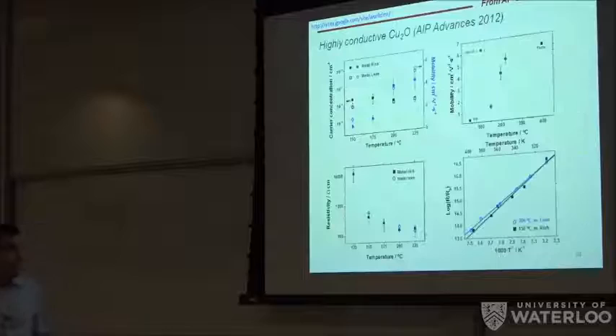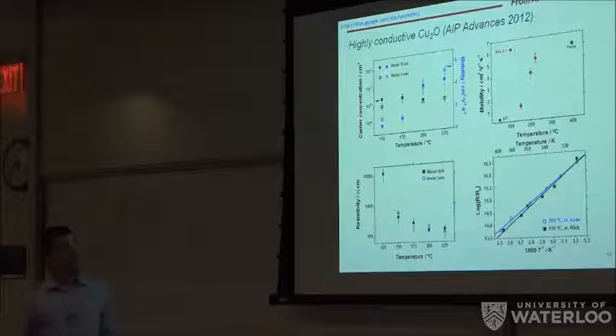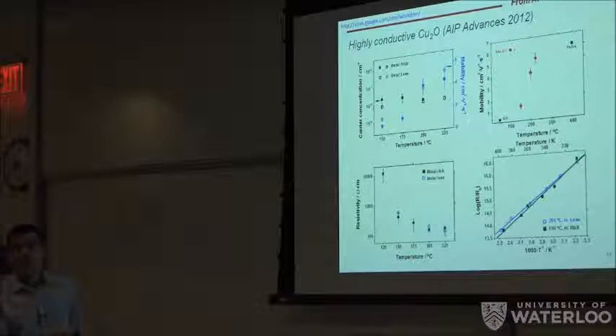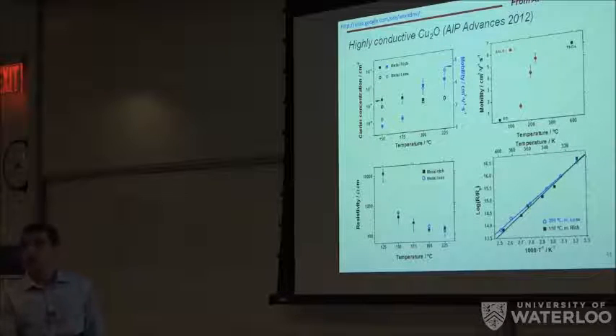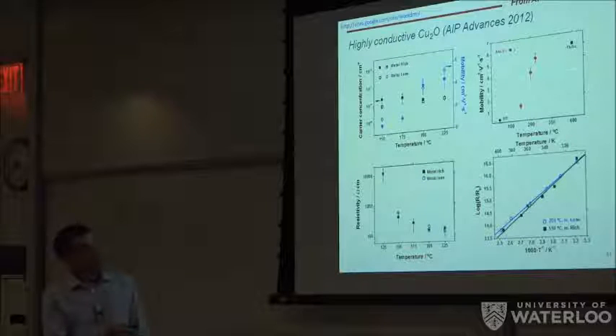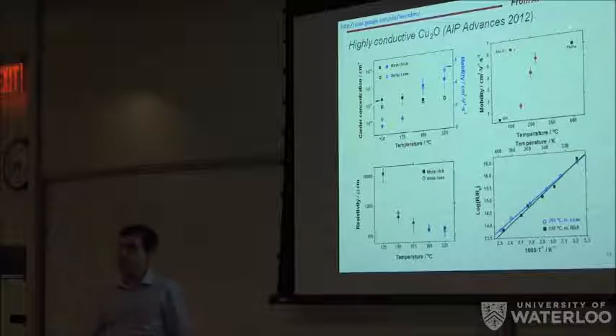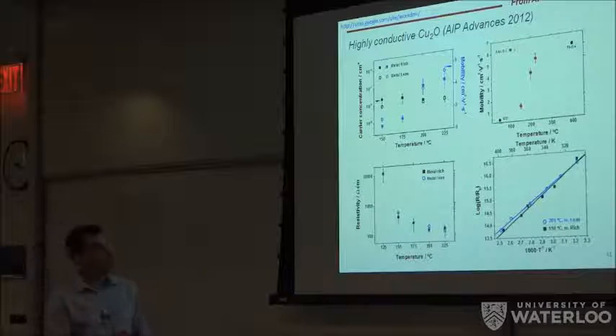The only difference is that by increasing the deposition temperature, the grain size was increasing, which led to a decrease in resistivity because, of course, mobility increased with the deposition temperature. And if we look at this mobility obtained at 225, it's quite remarkable because you can compare it with the mobility obtained for films deposited by electrodeposition, and it's quite low. And it's comparable to mobilities obtained for cuprous oxide films obtained by thermal oxidation at 400 degrees. So we're still almost 200 degrees lower in temperature, and we managed to get high mobility and relatively high carrier concentrations as well. You will see that this is 10 to the 16.